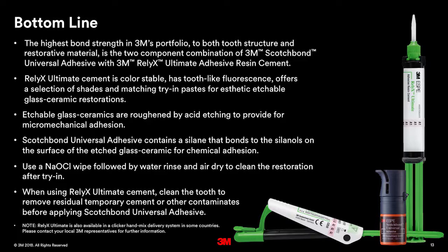Etchable glass ceramics are roughened by the acid etching to provide for that micromechanical adhesion. Scotch-Bond Universal Adhesive contains a silane that bonds to the silanols on the surface of that etched glass ceramic for chemical adhesion. Use a sodium hypochlorite wipe followed by water rinse and air dry to clean that restoration after the try-in. And when using the Relyx Ultimate Cement with Scotch-Bond Universal, make sure you clean the tooth, remove any residual temporary cement or other contaminants before applying the Scotch-Bond Universal.